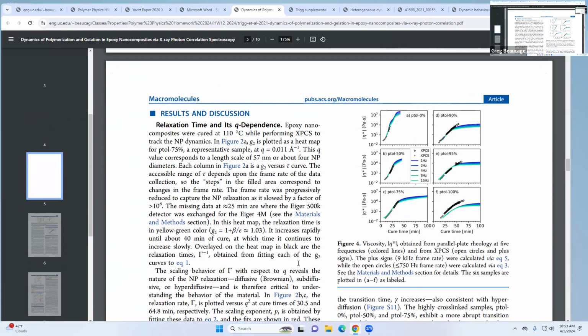So that's really powerful because you're taking a bulk measurement at macro scale that we can see, and you're correlating it down to some physics at the nanoscale. Huge range of length scales where that behavior is correlated. But you also have this big bulky viscometer, right? And then you have just the beam going through. That's true. The rheometer costs probably $20,000 and the X-ray beamline costs $500 million, something like that. It's a little bit more.